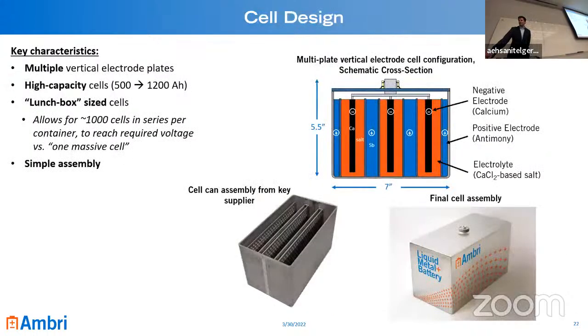Yeah. So the cell's configured like this, as I flashed up earlier. We have these bays where the particles of antimony are placed. You can see an actual cell positive current collector housing here, and there are areas where the antimony particles are loaded. The cell is filled with salt, and then the lid is placed onto the cell with the vertical negative electrodes. And so the salt's easy. Salt just floats around. The more challenging one is the calcium electrode, which is in a liquid state.